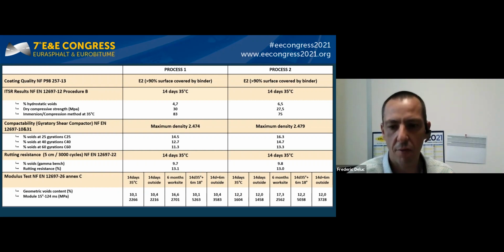whatever the number of gyrations, 25, 40, or 60. This clearly confirms that the material can be used in different thicknesses, thick, thin, or very thin. With regard to rutting, the two processes are identical, with 13% of rutting after 3,000 cycles.